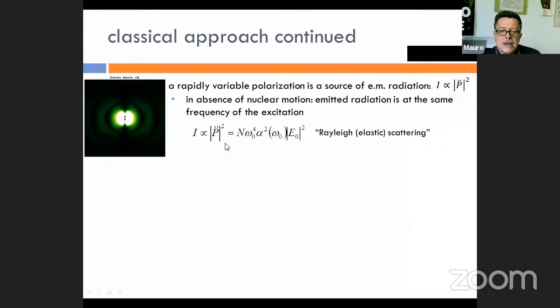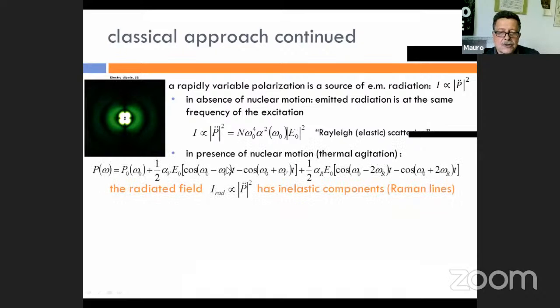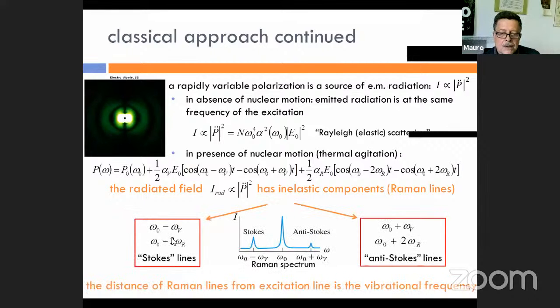So if we examine the polarization, we see that in absence of nuclear motion, we have only emission at the excitation frequency, and this is called elastic scattering, that is light irradiated at the same frequency of the excitation field. But in presence of nuclear motion due to thermal agitation, this is the new expression of the polarization, and then the radiated field has new components, which are the Raman lines of the system. The new components are at the combination frequencies.